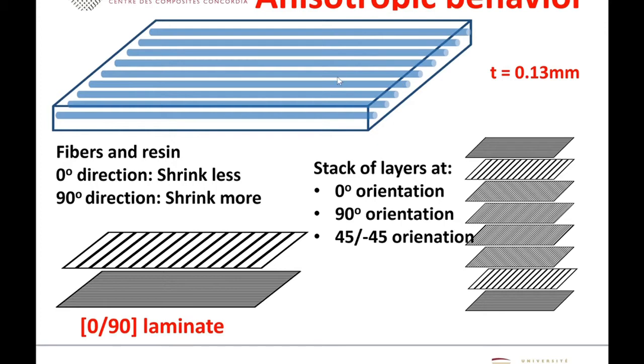Now you may wonder, suppose you have a thing like that, how do you make an airplane out of that? The way people make a structure is that they lay many of these layers together. For example, you can have a layer at 0 degree, another layer at 90 degree, another layer at 45 degrees and minus 45, and so on. By stacking many of these layers together, you can build up a structure. Eight of these layers can build up about 1 millimeter. So for an airplane skin of about 3 millimeter, you need 24 of these layers. That's the way people do it in the case of making an airplane.